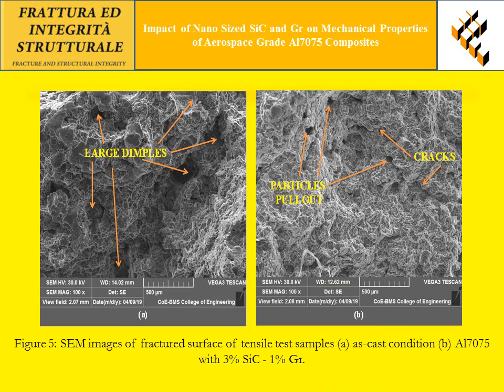The figure shows the SEM image of the fractured surface of tensile test samples of base material and hybrid Metal Matrix composites. From the fractography study, it is observed that increase in the weight percentage of silicon carbide and graphite content changed the kind of failure from ductile to brittle. Generally, this could be clearly observed from the deformed regions and dimples present within the fractured area.